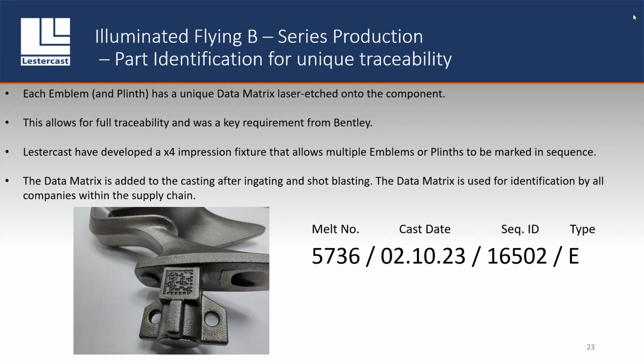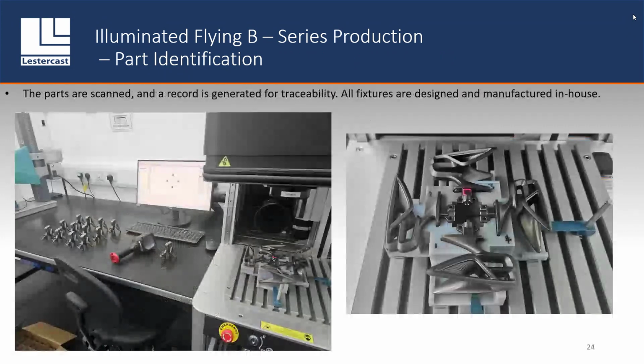So you'll be able to see when you come and have a look at some of these castings here, particularly this one. This one's got a data matrix on it, but it sits below the line here, the plinth, so you can't see it unless you take it apart. So this is all done at Lestercast. Once the parts have been manufactured, they go through this process, and we have a unique laser marker that allows us to put this on, which you can see here. This is a fixture that we designed in-house. Allows us to do 4 parts in a sequence, and we have a scanner here which is linked to a record, so we can zap it and put it onto a record, so that suddenly becomes a live part, if you will, and then we can track it through, and it stays from a traceability point of view.